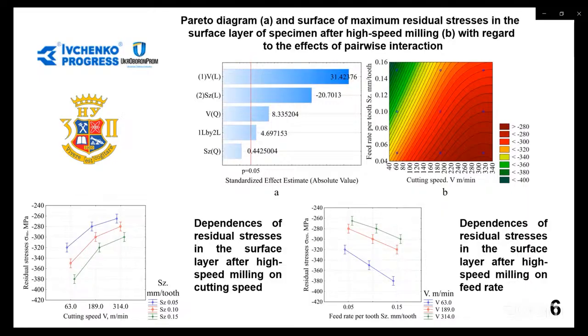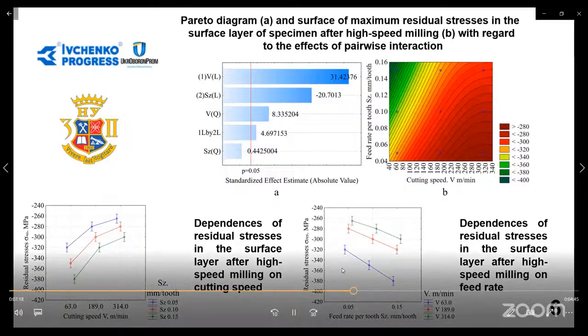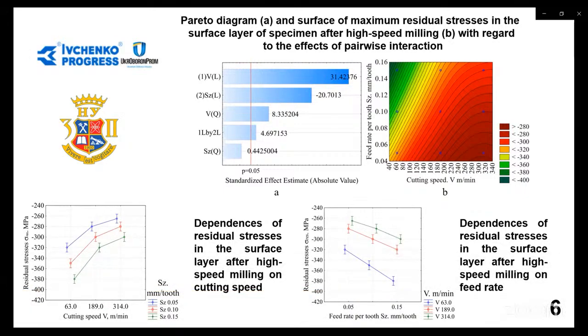Thus, increasing the cutting speed in the range of 63 to 190 meters per minute was accompanied by a 30–35% decrease in the value of compressive residual stresses. Further increase in cutting speed was also accompanied by a decrease in the value of compressive residual stresses in the surface layer. However, their value decreased by only 5 to 7%. In the range of feed rate variation of 0.05 to 0.15 mm per tooth, the value of compressive residual stresses monotonically increased by 15 to 19%, depending on the cutting speed. The observed regularity was explained by intensification of the thermal factor of residual stress formation as the cutting speed increased and the force factor as the feed increased.